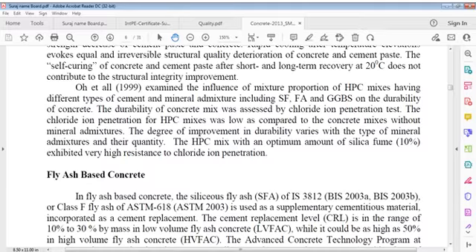Oh et al. (1999) examined mixture proportions of high performance concrete mixes having different types of cements and mineral admixtures including silica fume, fly ash and GGBS on durability of concrete. Durability of concrete mix was assessed by chloride ion penetration test. Chloride ion penetration for high performance concrete mixes was less as compared to concrete mixes without mineral admixtures. Degree of improvement in durability varies with type of mineral admixtures and their quantity.